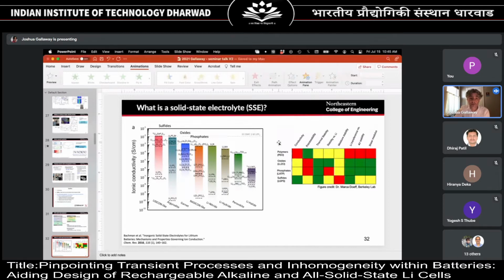This is a very famous figure from the scientific literature that shows the conductivity of different solid electrolytes. And this dashed line at the top of the curve is the liquid electrolyte found in lithium-ion batteries. And look, these solid sulfides have conductivities that are almost the same, and in some cases higher than liquid electrolyte. This is a log scale that's going across 10 orders of magnitude. This line is at 10 to the minus 2 Siemens per centimeter. Now I want to point out, this is pretty much the last point that I'm going to make. That is amazing. These are solid materials, and they conduct lithium ions faster than liquids.